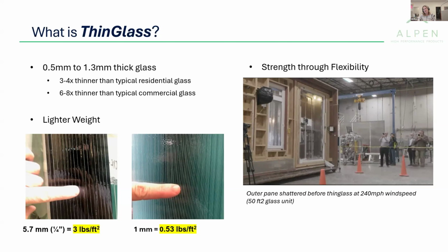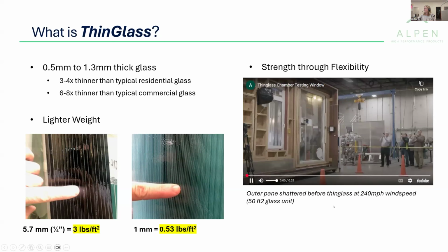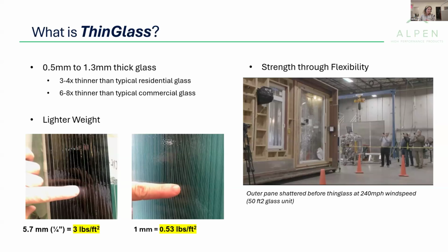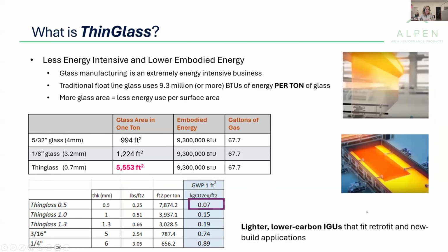The strength of the product really comes through the amount of its flexibility, that it truly bends. So in the video that I will replay, we took a 50 square foot unit that's a quad thin glass. So 2 panes of 1/4 inch glass, 2 middle panes of thin glass, and we subjected that unit to 240 mile-an-hour wind speed. And we carefully monitored the deflection of those 2 inner thin layers. And we were surprised to see that when it reached its final breaking point, it was actually the 2 panes of 1/4 inch glass that broke first and then shattered through the thin glass layer. So it's very capable of meeting the design loads of the built environment.